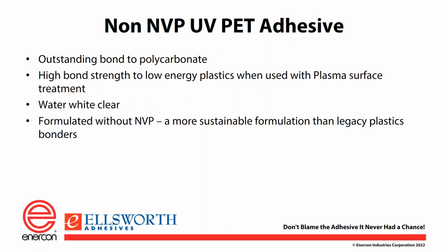Non-NVP UV PET adhesive. For many years, people were bonding to low surface energy plastics by modifying their acrylic-based UV cure material with N-vinyl pyrrolidone. Vinyl pyrrolidone is actually, I guess, a solvent to the surface. It allows a little bit better bite for the UV cure to the material. So in the case of PET, for example, it usually provides a substrate to substrate failure with PET.